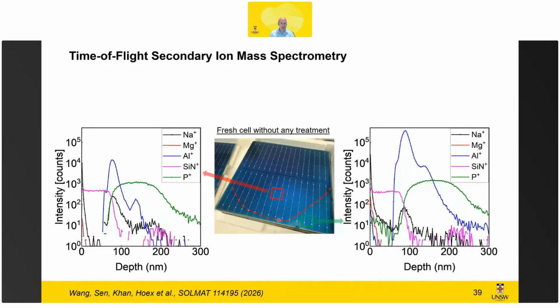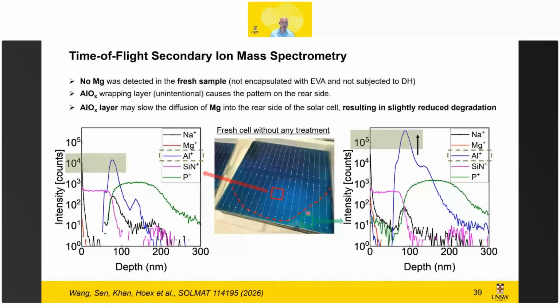And then the main difference, the pattern that we saw, was actually due to a difference in AlOx layer. So aluminum oxide, which is well known to have potential wraparound, particularly if you use ALD, atomic layer deposition, as the manufacturing tool, which is the standard, and use back-to-back loading. And we saw that areas with a thicker AlOx film showed less degradation. They still showed degradation, but it was less than what we saw before. So we postulated, but again, all the details can be found in the paper that is available free of charge on the link provided on the final slide.